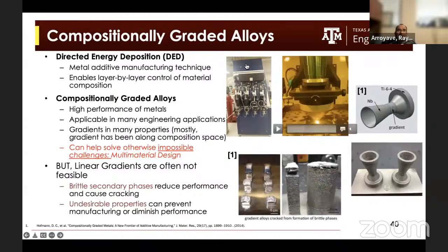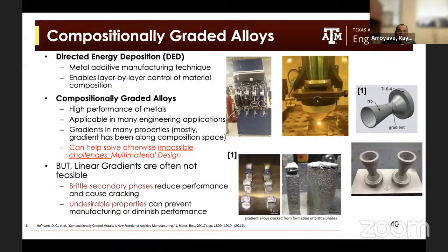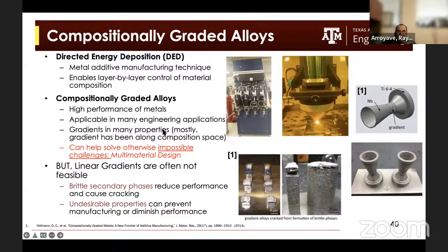So, how do we do this in practice? There are many techniques for multi-material printing, but in our work, we have used directed energy deposition. In this case, you print a material on a layer by layer basis, but what is different from additive manufacturing is that we're actually depositing the material and the power or energy at the same time, right? So we basically print by shooting a beam of powder and melting it on the fly and hoping that it sticks on the substrate so we can build a complex three-dimensional shape on a layer by layer basis. There are many possible engineering applications, and they, for example, can enable multi-material design.